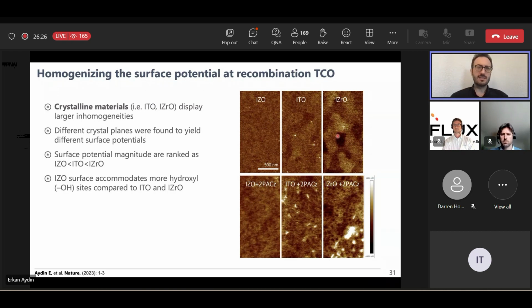crystallite. Basically, these are polycrystalline materials, ITO and IZRO, and in polycrystalline materials, there are different grains and they have different grain orientations on the surface. And we understood that they already have different potential distributions. And plus, if you anchor your SAMs on the surfaces, they also follow and mimic this trend.